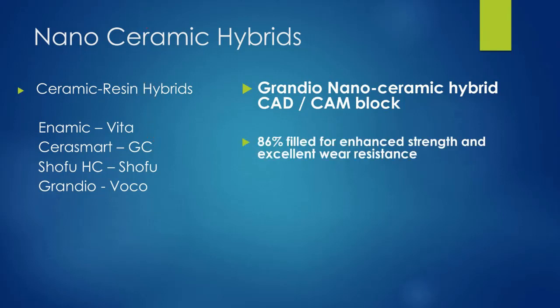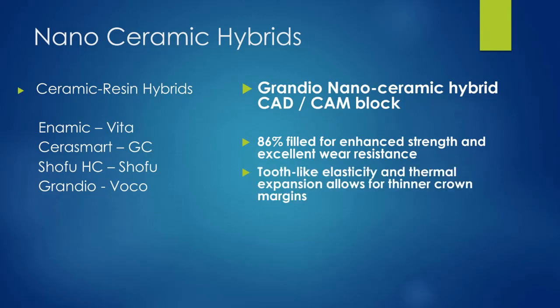So what we see is that with the Grandio block by Voco, this is an 86% filled material. So not only do we get enhanced strength, we get really good wear resistance, we get absolutely beautiful polishability, and we also can put a silane primer onto this product, and we're seeing enhanced bonding with this product.